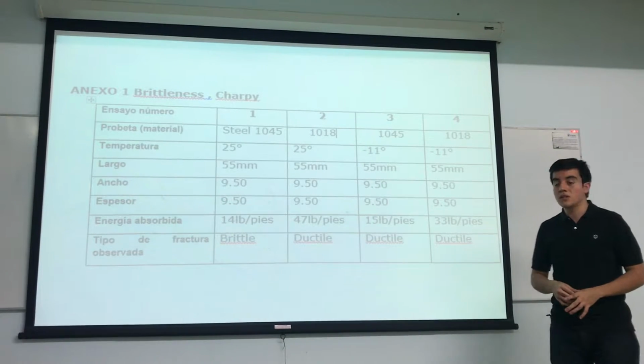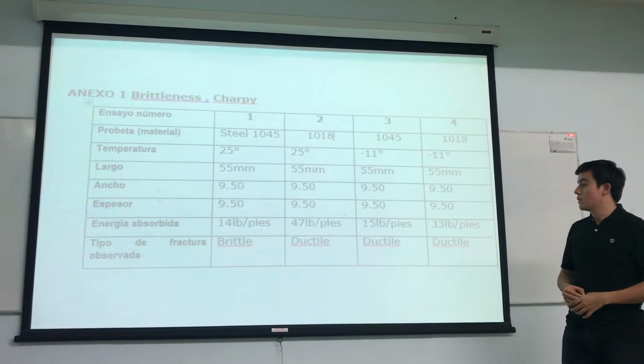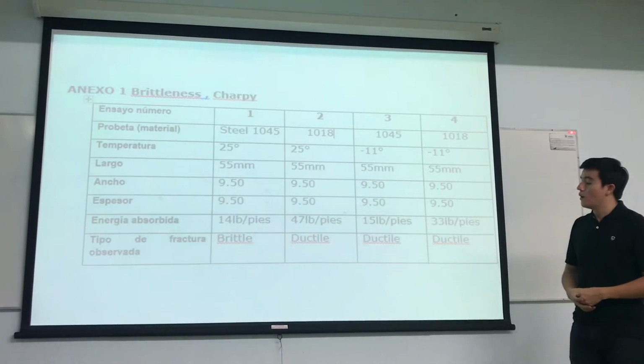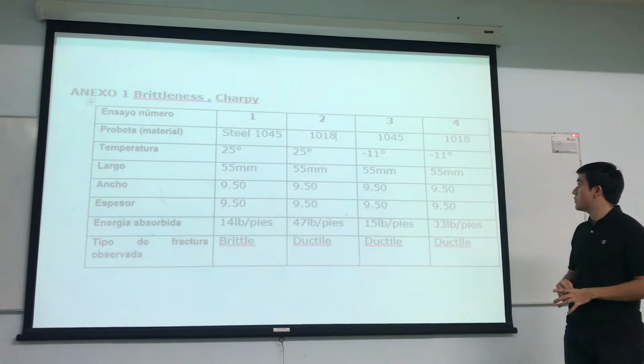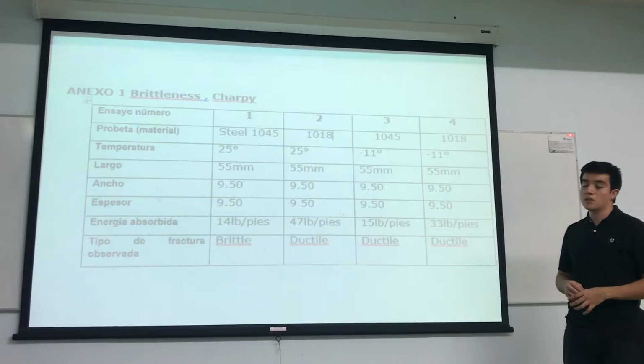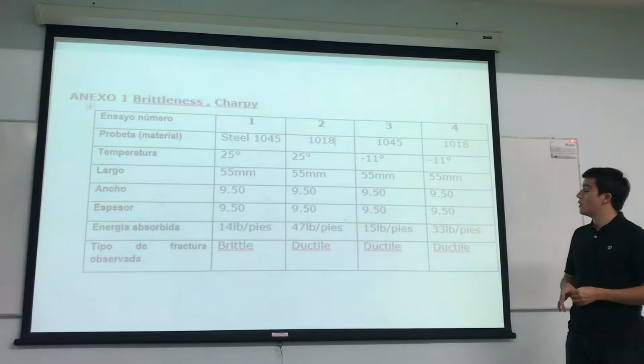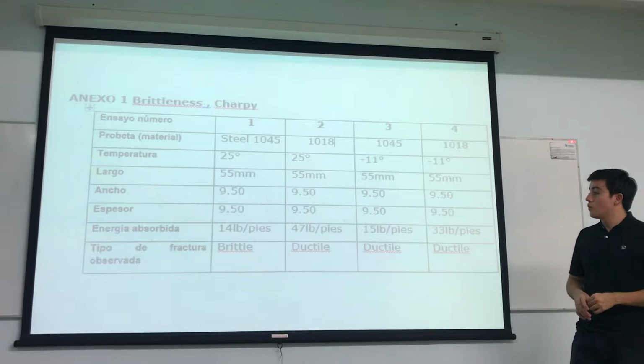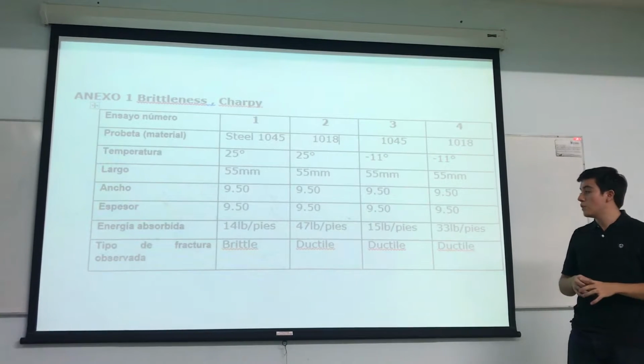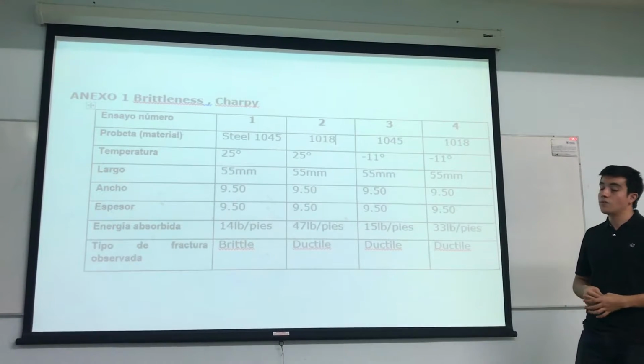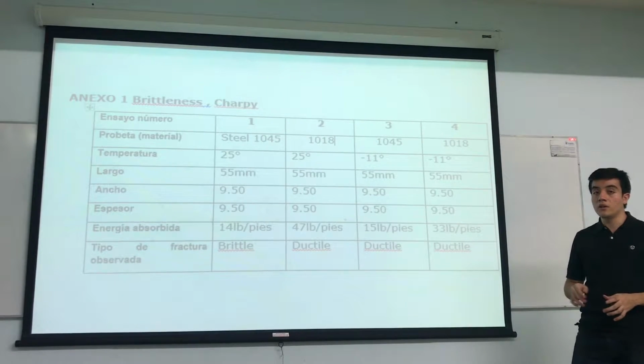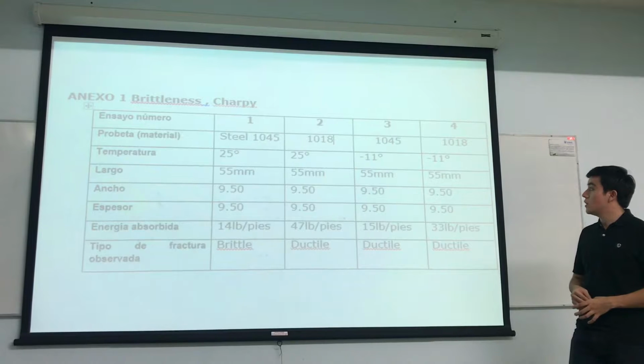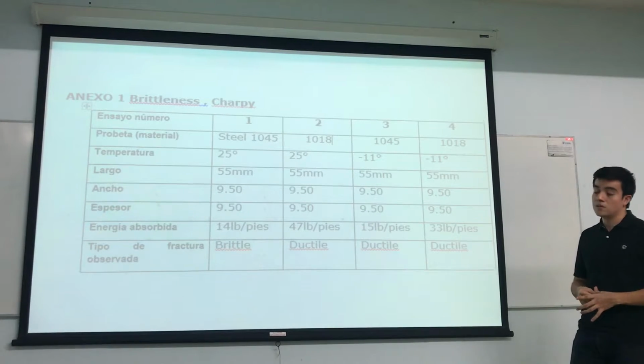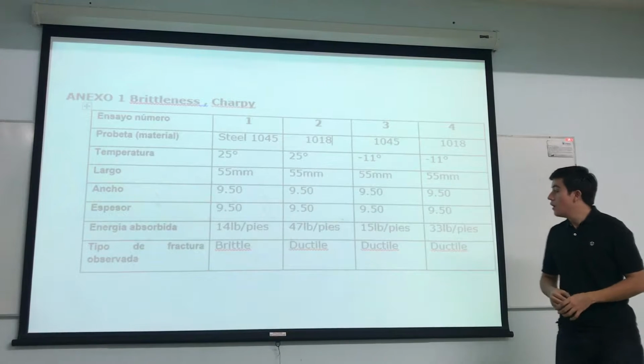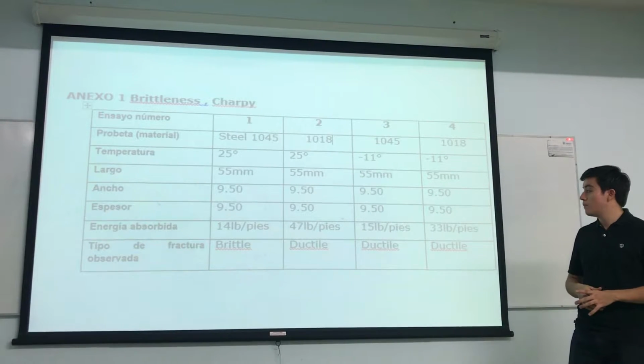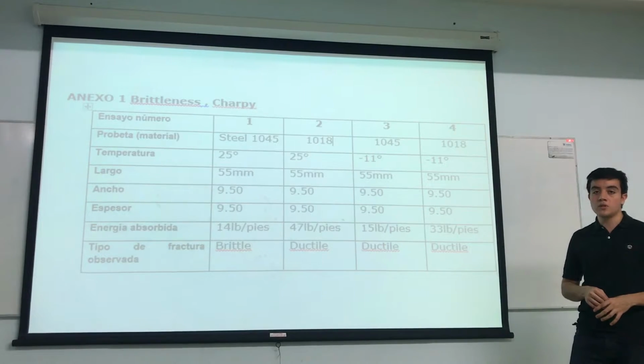We used the steel 1018 also at 25 degrees, and we can see also the absorbed energy. We did the same process for the steel 1045 and the steel 1018, but we changed the temperature of these pieces to minus 11 degrees. Seeing the results of the pieces, we can determine the type of fracture. For the steel 1045, we have a brittle fracture that has no or little plastic deformation, and the other 3, the steel 1018 at 25 degrees and the other 2 at minus 11 degrees, have a fracture of ductile type that has plastic deformation in the pieces.